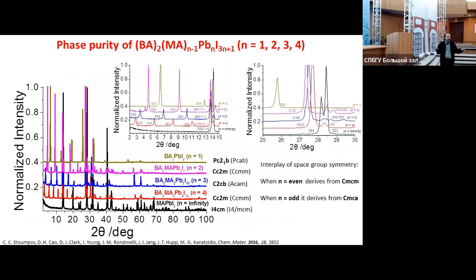And just to convince you that this is not one crystal that we got lucky to get right, this is how the powder diffraction spectra look. The materials are chemically pure, and that's the important part. If you want to do application of any kind, you need to make the material pure. That's from the chemistry perspective, this is what you need for anybody to believe you. And you will see that you have perfect ordering. Interestingly, the number of small peaks below the peak of the bulk phase actually give you the number of layers. So you have 4 peaks here, you have 4 layers, 3 peaks, 3 layers, and so on. That's accidental, by the way, but it's very helpful when you try to characterize the materials.